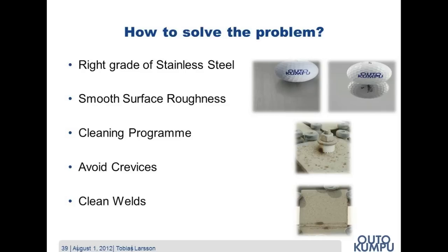Then you should try to have as smooth surface finish as possible. A cleaning program is very important since we don't have the rain that naturally cleans the material. You should also try to avoid crevices, since these are created by high levels of dust, sand, industrial particulates, and even leaves, and this is not always considered during site assessments, even though corrosion is more likely to initiate in these areas. And finally, you should always clean and treat your welds properly.